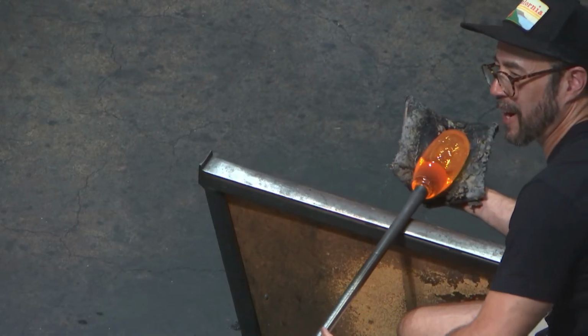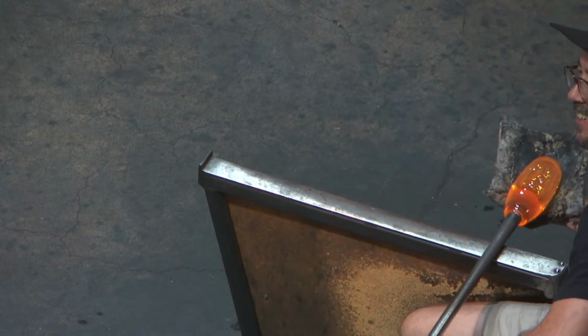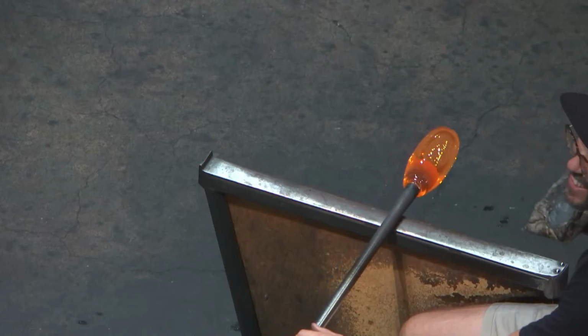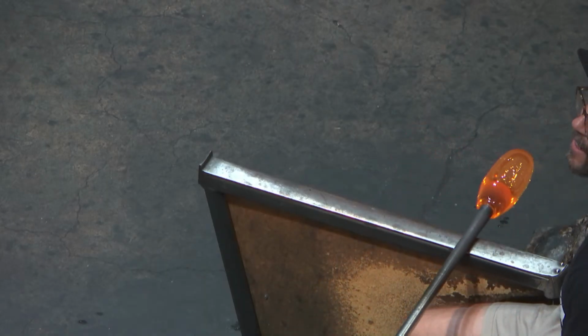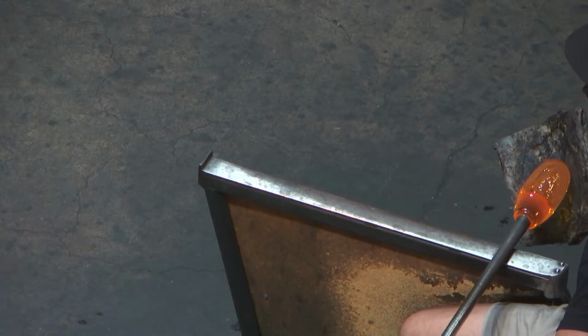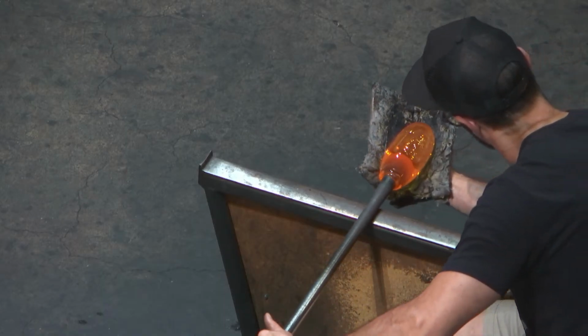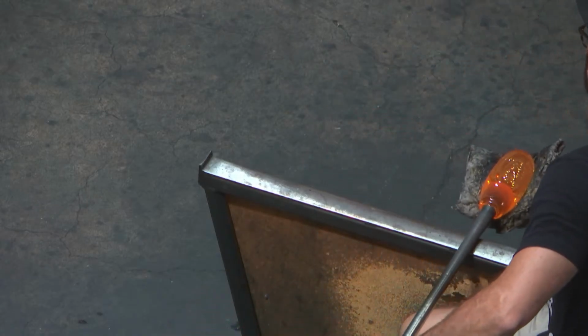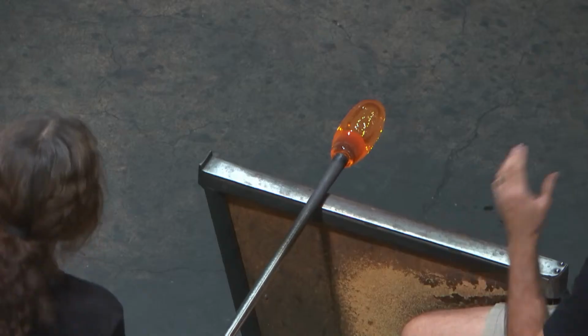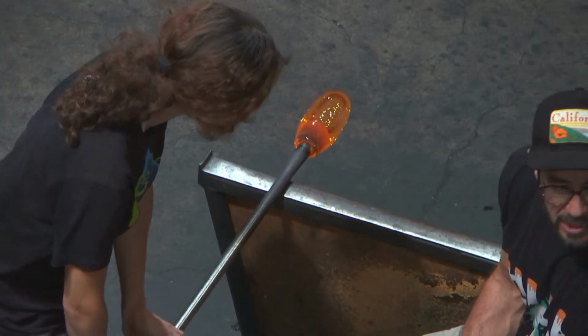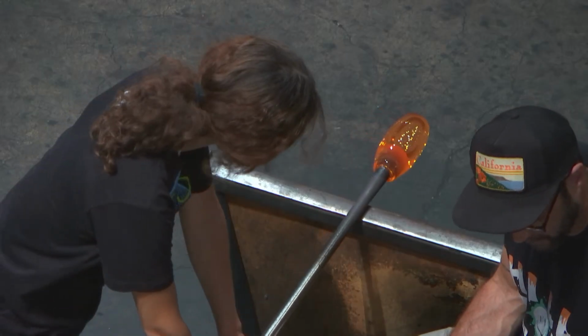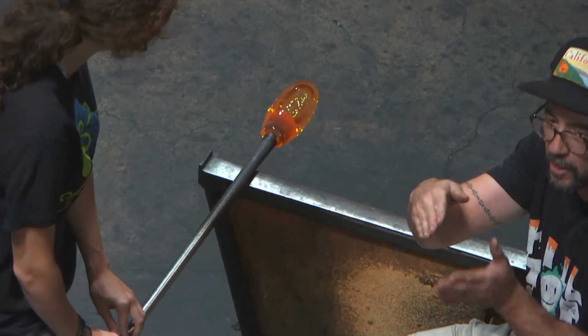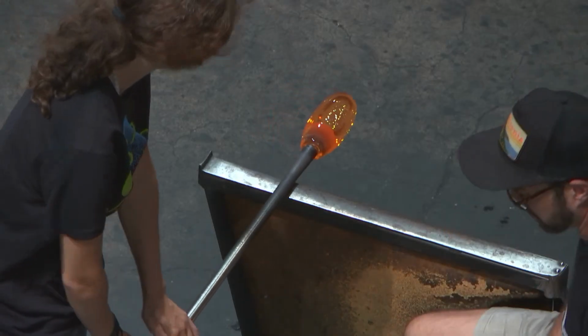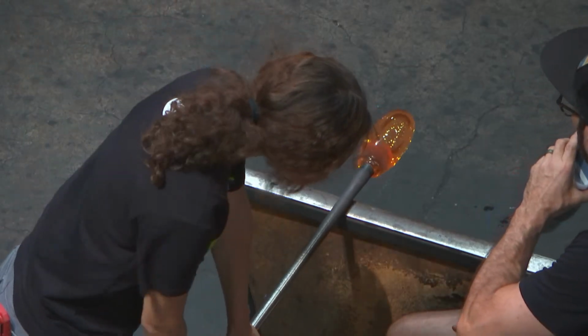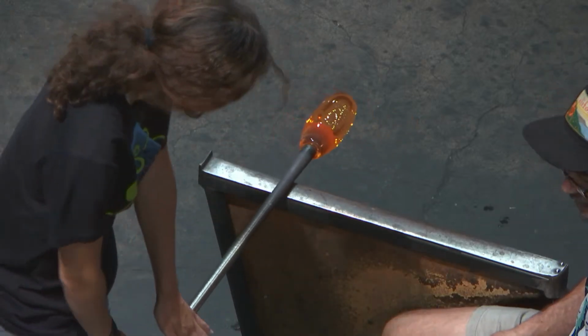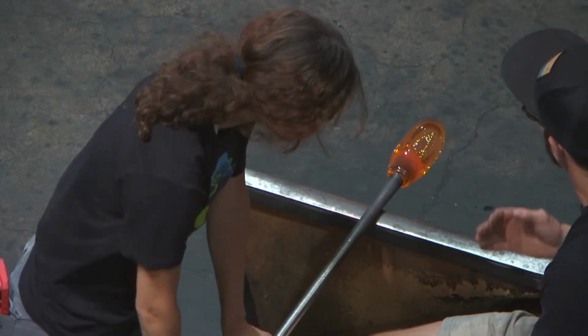So Gabe at the bench is telling Stina when to blow into the pipe and when to stop blowing. And he's using his best judgment and his experience to know when to tell her to stop. We don't want to blow the bubble too thin. If the glass gets too thin, it loses all of its structure. It's a weird way to describe, but when glass is hot, if it gets thin, it can wrinkle if it gets too hot, and then it'll fold over itself and mess up the pattern. You're also at more of a risk of the glass breaking if it gets really thin, because the thinner it is, the faster it will cool down, and if it gets too cold, it will crack from thermal shock. So there's a lot of things that this team is balancing right now. There's a lot of multitasking and a lot of different nuances in glass blowing.